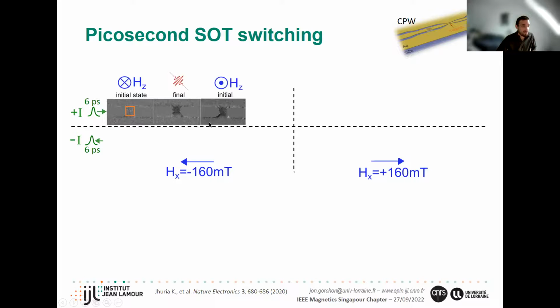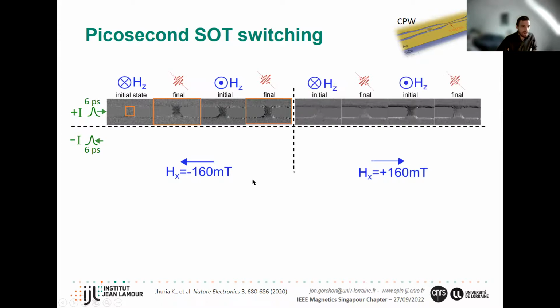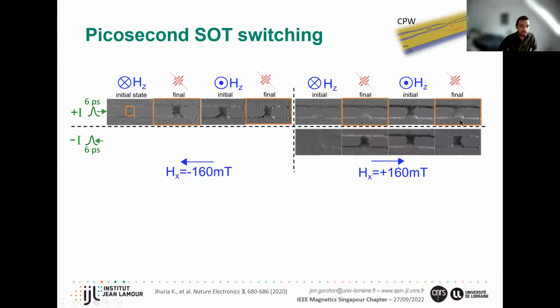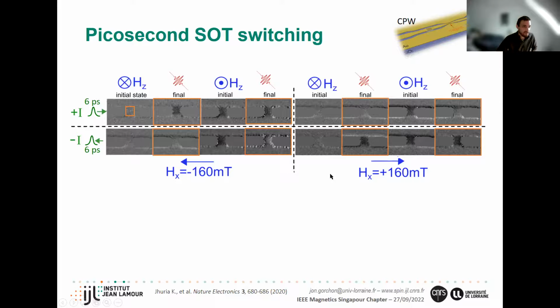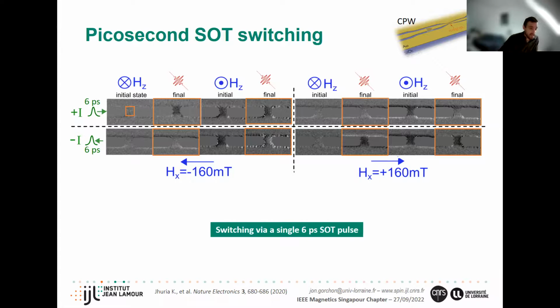If we start in the opposite direction and we send a single shot, it doesn't switch. And basically we can keep shooting and the final state doesn't change. So irrespective of the initial state, the final state is determined by the current and the field polarity. If we switch the field polarity, you can see the final state is now opposite. If we switch now the current, we get again the opposite final state. And finally, the last quadrant, you get again the opposite. So this is perfectly in agreement with spin orbit torque switching. And we're using 6 picosecond wide electrical pulses, which was pretty surprising when we got this result.